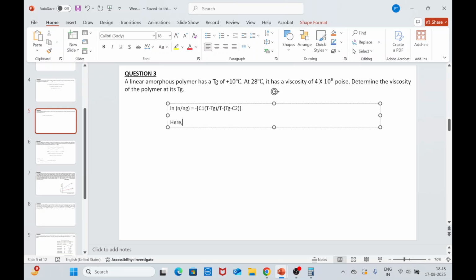Here the values of C1 and C2 are 17.44 and 51.6 respectively. So these are the universal constant values. So this is the empirical relationship, and C1 and C2 are the universal constants. So based on this, you just need to plug in these values and calculate the viscosity at the glass transition temperature of the polymer.